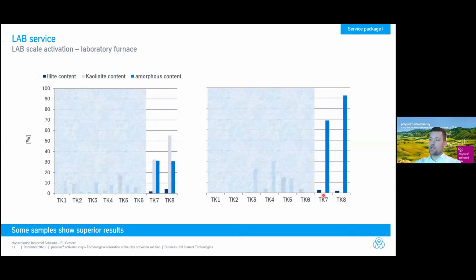But we wanted to activate the kaolinite, and this is what you see here. There is no kaolinite anymore in this sample of the activated clay. All the kaolinite is transferred into the active amorphous phase. This is what you see here.